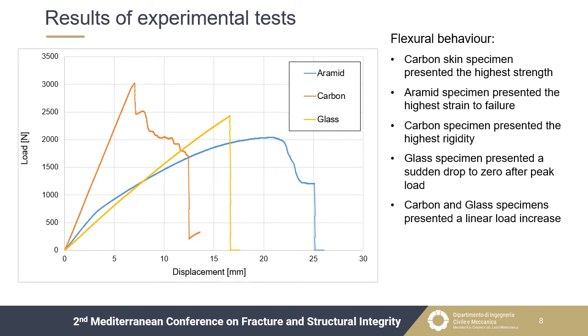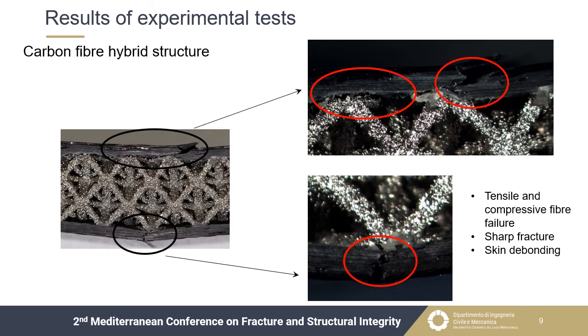The highest flexural rigidity, evaluated as the slope of the load increase section, was obtained by the carbon specimen, while the lowest by the glass one, even if the aramid specimen presented a minor slope in the second tract of the load increase. Some images of the fracture zone were taken through an optical microscope to inspect the fracture mode.